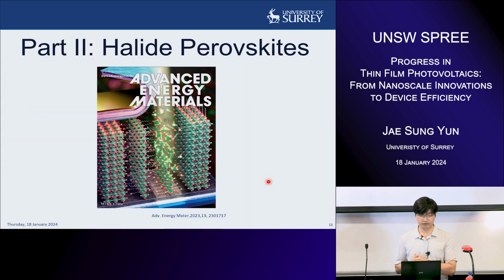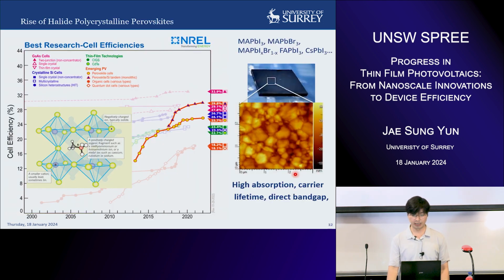And then I moved on to halide perovskites. The material is still polycrystalline, as you can see from the image here. It's got an absorber around 500 nanometers thick. It's got a very high absorption coefficient, especially in the visible wavelength region, and it's got a very high carrier lifetime compared to other thin film technologies, and it's a direct bandgap material. If you see the progress of halide perovskite solar cells, it evolved quite fast.